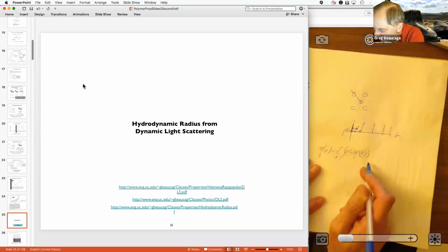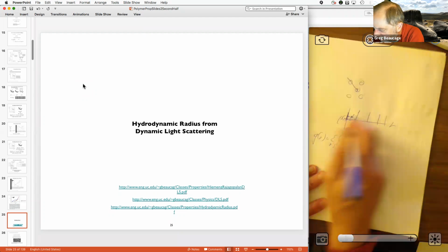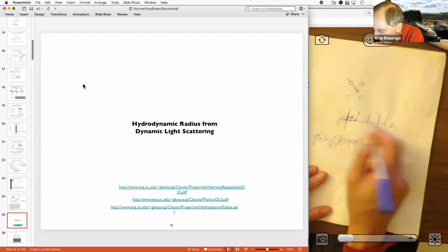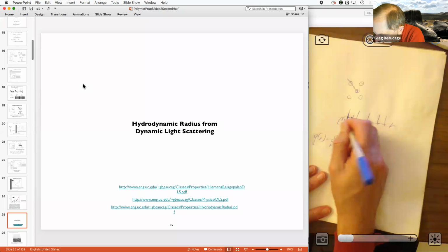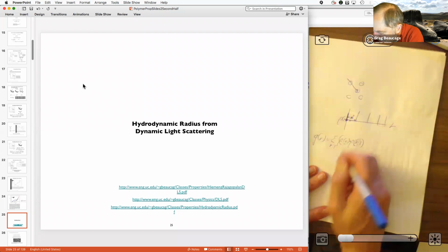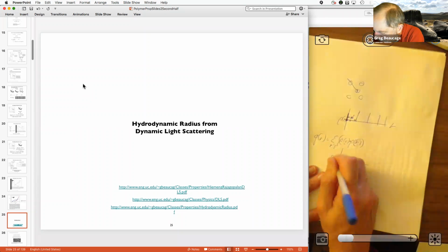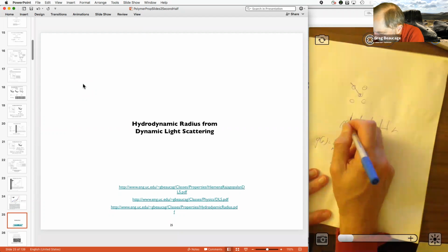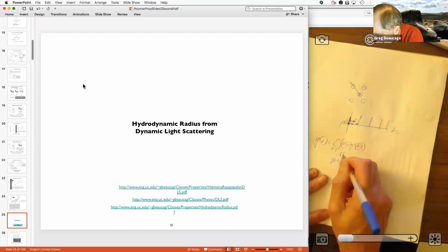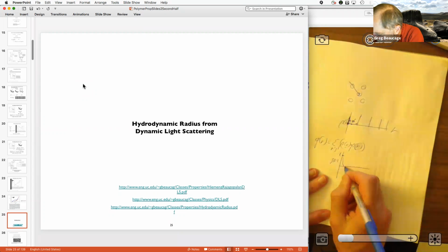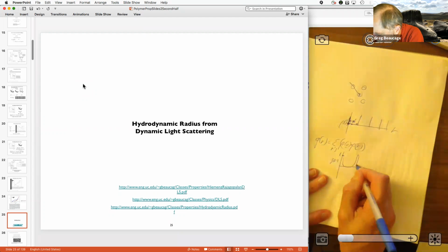And for this case, it's going to look almost like the same thing as the density. So if you're at 0, you're always on the spikes. You always have G of r is 1 at the start. And then there's usually some smeared outness to this, so it'll drop down with an exponential, and you'll go along, and then there's the other atom. So it'll be like that for a crystal. It'll just keep going.